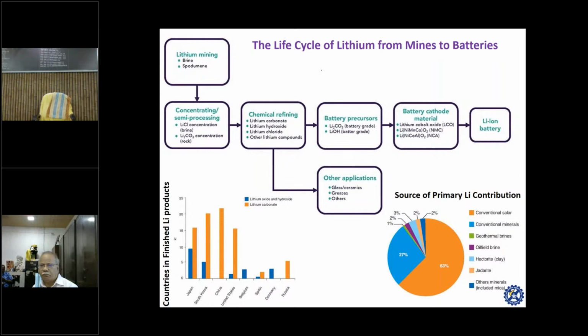So when we move from the resources, we have to understand that the life cycle of lithium from mines to battery is very important. How does it come from the mines as brine or spodumene, and then get pre-concentrated in the brine as lithium chloride and in the rock as lithium carbonate. So you need to do chemical processing of it. So you get lithium carbonate, hydroxide, chloride, depending upon the kind of acid or precipitation agent you are using, and you make the precursors, that is lithium carbonate, lithium hydroxide. And then you transfer the matrix stoichiometrically into a battery cathode material, giving you lithium cobalt oxide or manganese oxide or aluminum based material, and finally that comes as a battery.